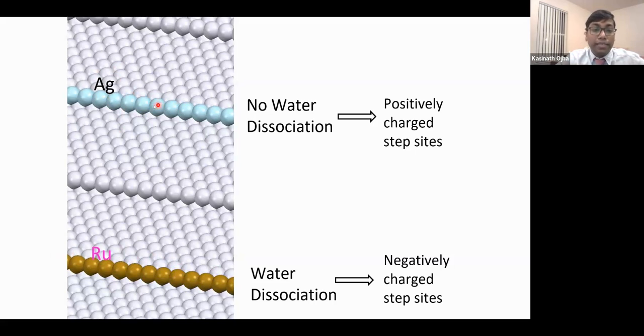They are not neutralized. We did this experiment to check if they really are positive or negative. As those are positively charged, they somehow influence the water structure on the terrace, and that leads to a much smaller double layer capacitance. While when they are negatively charged and OH is there, OH is really coordinating with water. So the water structure on the terrace becomes more solid, and that's why much more ion interaction on the terrace happens, and your capacitance really goes high.